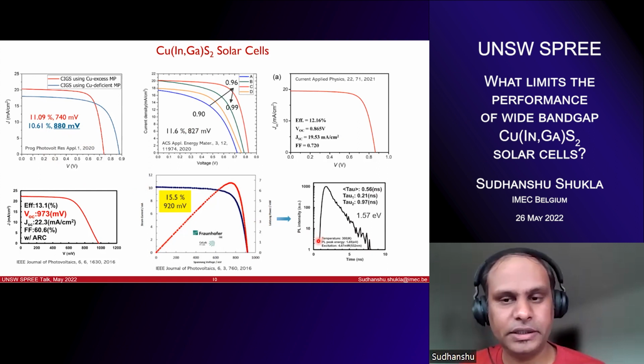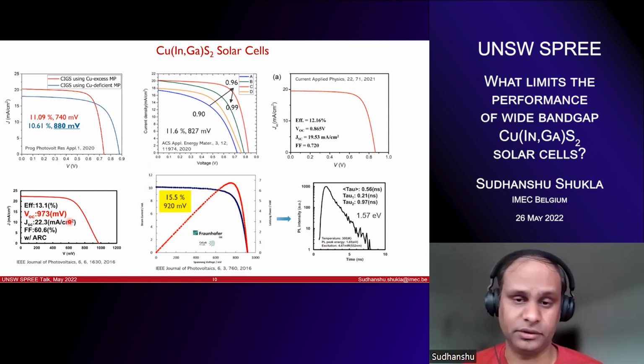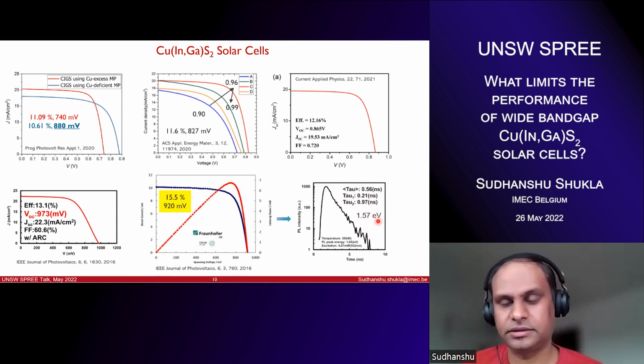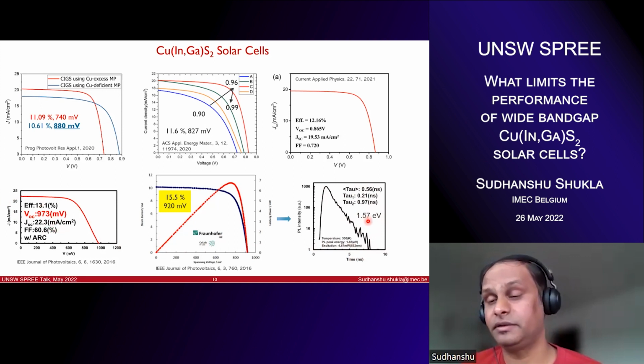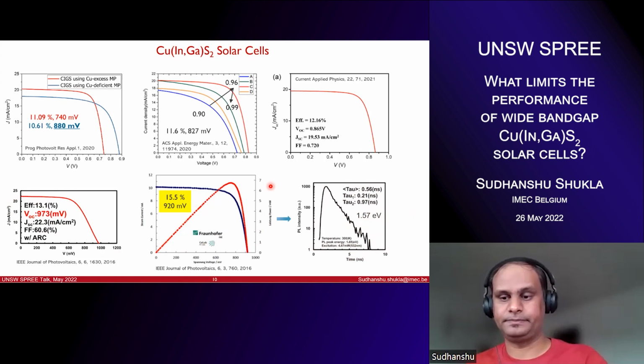But one thing I want to bring to your attention is that if you look at the optoelectronic quality of this absorber, the record absorber, for example, has a 973 millivolt VOC, which is quite good. The lifetime is very bad. And here they have shown there are two components, 0.2 and 0.97 nanoseconds. This is really bad. If you look at good CIGSe, or forget perovskites, the lifetime is very high, but these lifetimes are not at all good. Also, surprisingly, this lifetime is measured at 1.65 eV, while the solar cell performance is of a 1.57 eV absorber. So I don't really understand.